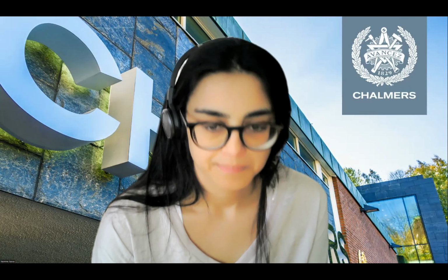Yes, so at the beginning we thought that the scale should be the same for both materials because they are both cerium based, but at the end, when reinterpreting our data, we found that it doesn't, and they have different length scales. Once we reported the London penetration depth on cerium copper silicon 2, we found that it was much bigger than the London penetration depth found on cerium cobalt indium 5, and as a consequence that changes the orders of magnitude of the form factor detected. I see. Okay, that explains it. I didn't think like that. That's a good point.